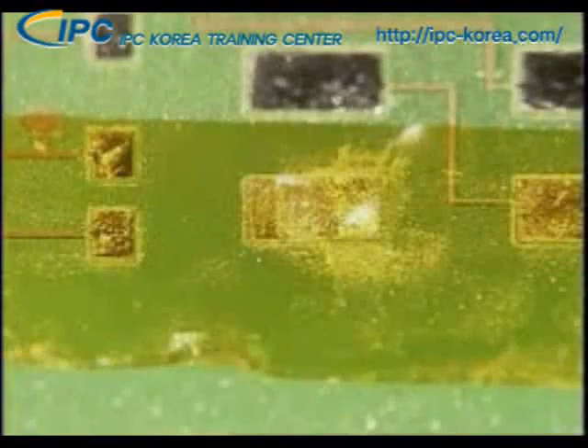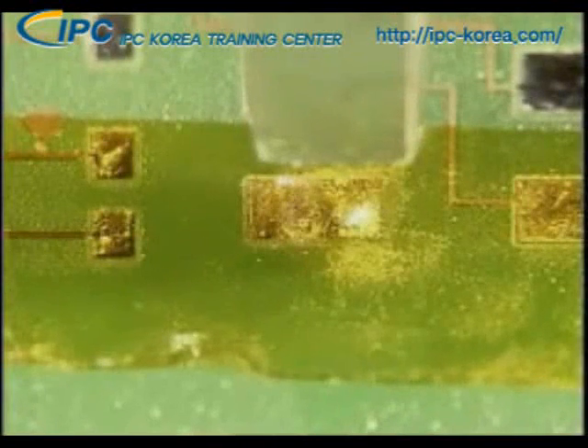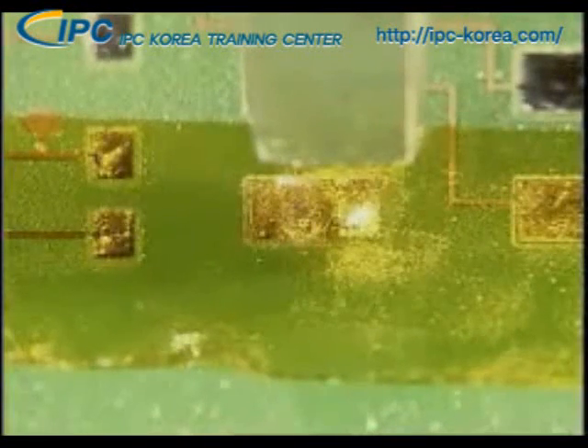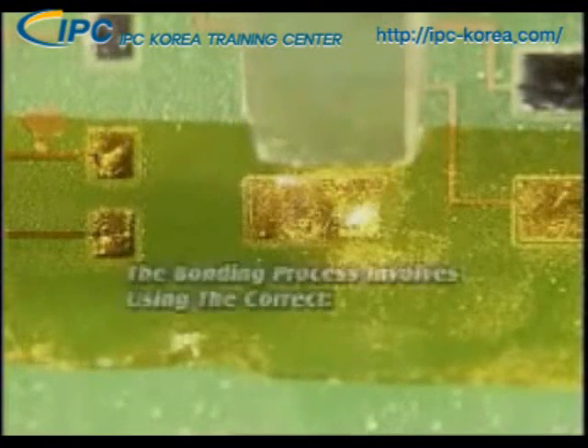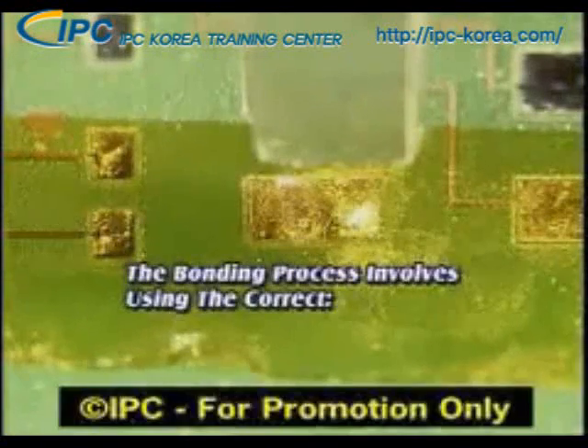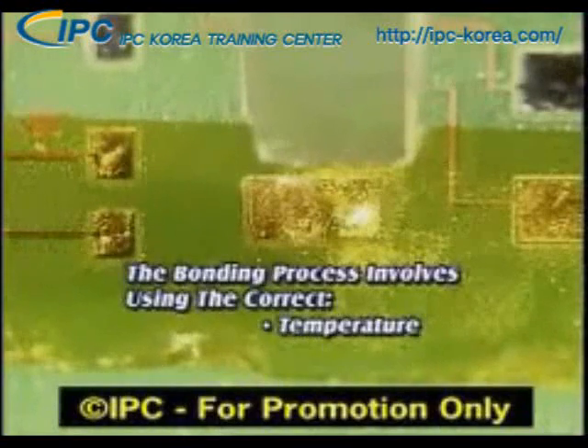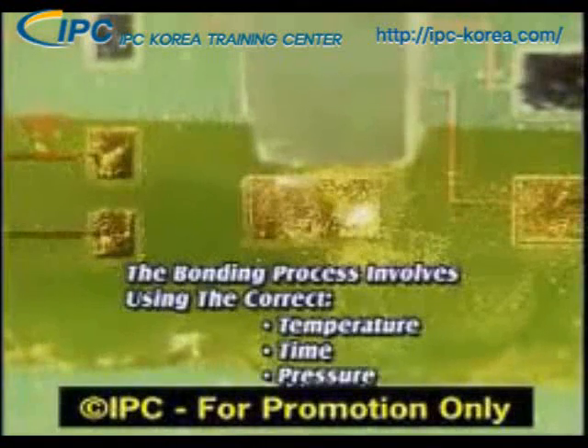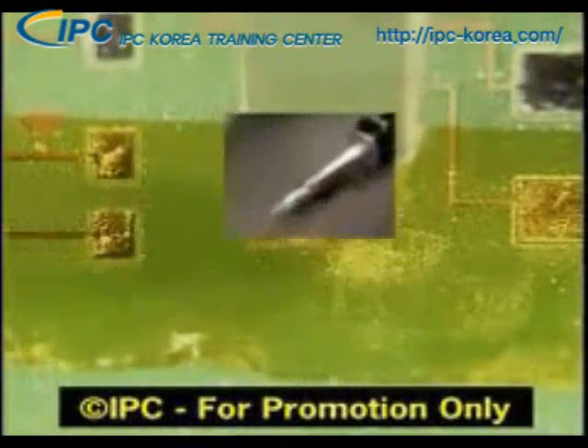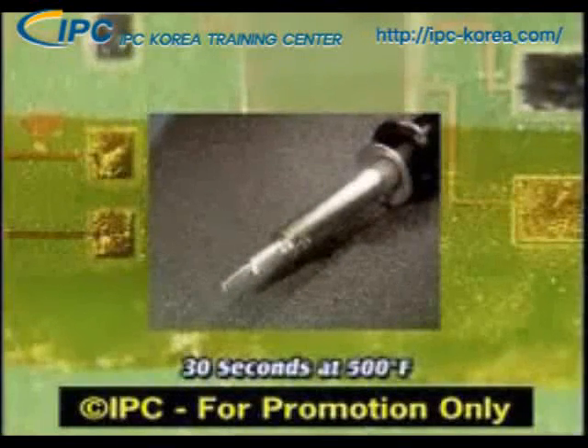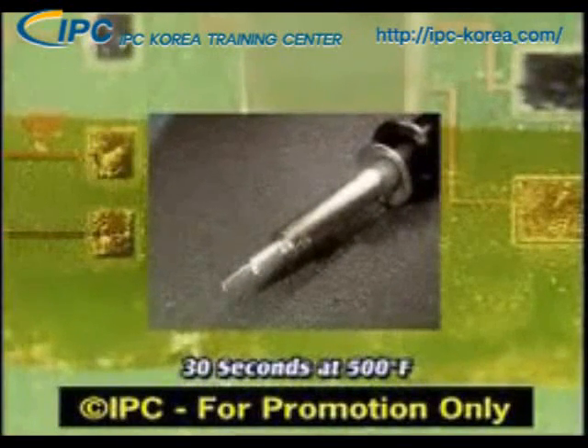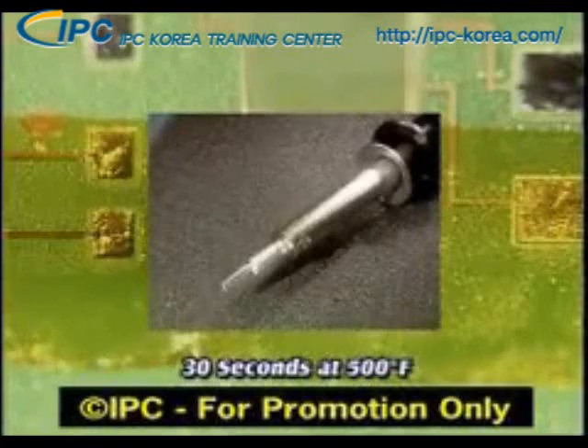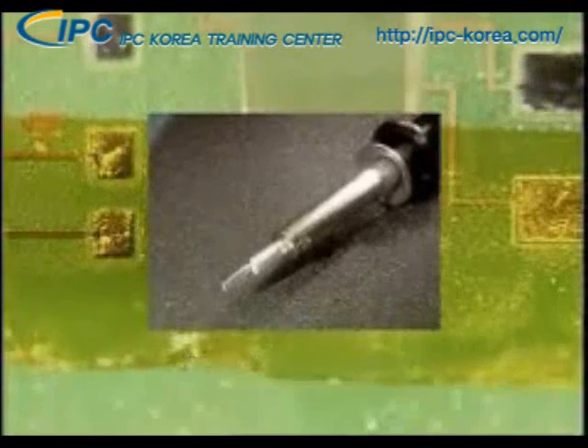Now we're ready to apply the heat with the hot bonding iron tip and actually bond the land back down to the board. It is important for you to understand that proper bonding procedure involves three things: temperature, time, and pressure. Bonding irons operate at 500 degrees Fahrenheit. Once the iron is placed on the land, the bonding cycle takes 30 seconds.